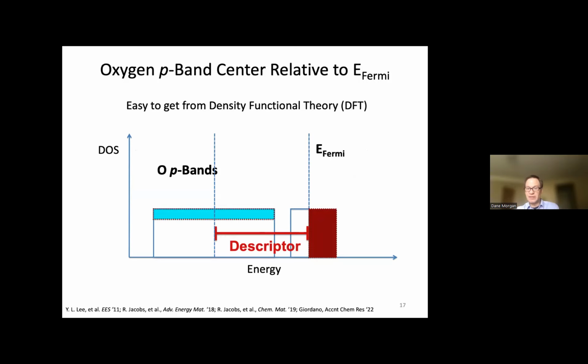And it is just the distance of the P-bands, the center of the oxygen P-bands, to the Fermi level. So if you calculate a density of states, here's a very schematic density of states. There's a region of the quantum states of the electrons that are associated with oxygen that we call the P-bands. And if we take the center of that, it typically has a certain distance from the Fermi level, which is the highest occupied level of the electronic structure. And we took this as the descriptor. That's easy to calculate, comes right out of a typical quantum mechanical calculation.